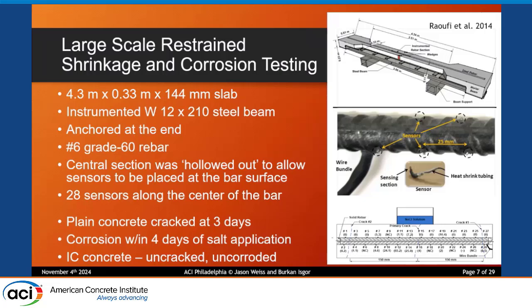All right? What I want to point out is the plain concrete sample, right? The concrete that the DOT was happy using as their standard concrete cracked at 3 days in this test. It was a glorious crack. There was much rejoicing when it cracked. The internally cured concrete didn't crack. Right? The one that cracked, the plain system, went into corrosion within 4 days of salt being applied. So if you can think of a situation where you've put out a new bridge deck, it cracks at 3 days, and 4 days after salt is applied, it starts corroding. What is the service life of that concrete? Right? We're starting a problem, right, by allowing those cracks to exist there.